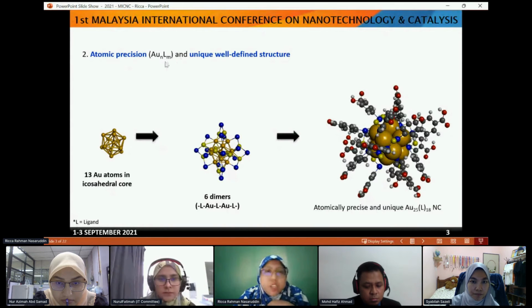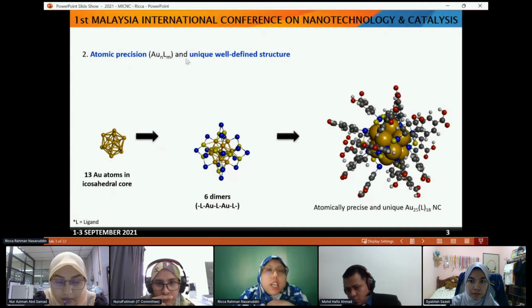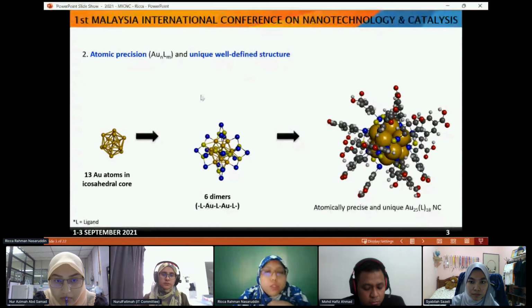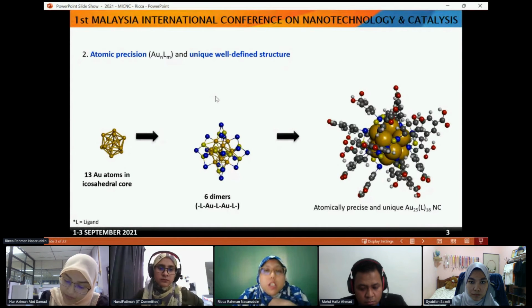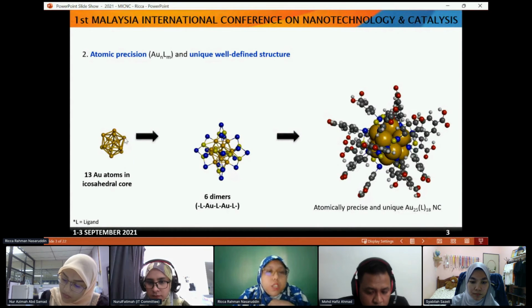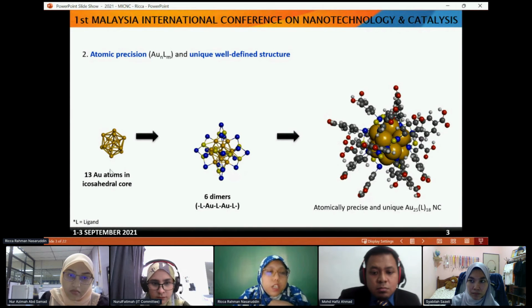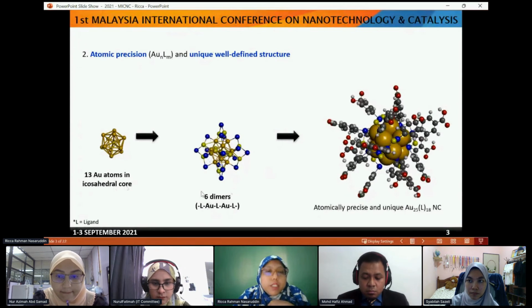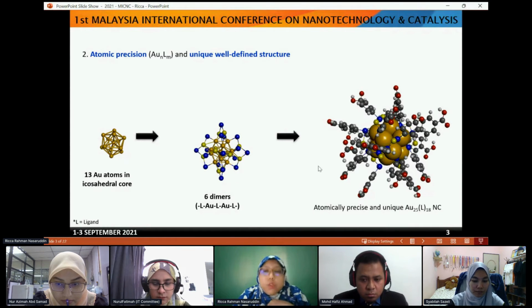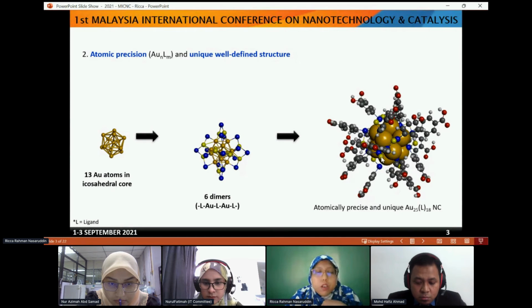What does it mean? It means you can know the number of gold atoms, and also the number of ligands. And it also has a unique well-defined structure. For example, the most famous ligand-protected gold nanocluster is Au25 with 18 ligands. It has 13 gold atoms in an icosahedral core, protected by 6 dimers. Each dimer has 2 gold atoms with 3 ligands. This is an example of the structure which I produced using molecular dynamics simulation with CHARMM force field.